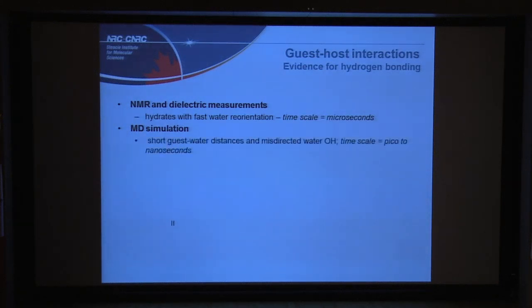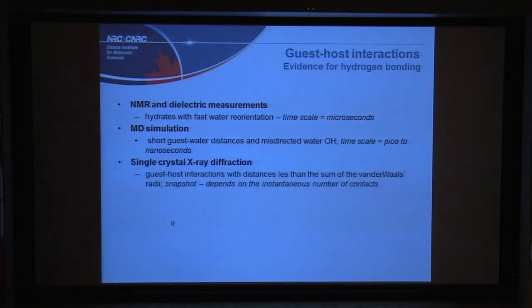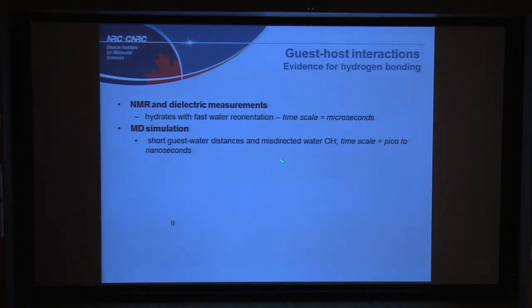More recently, we can use MD simulation, and what we do there is look for short guest-water distances, shorter than one would expect, and also misdirected water OHs. So we're looking for guest-host hydrogen bonding. And this is done on a time scale of pico to nanoseconds.